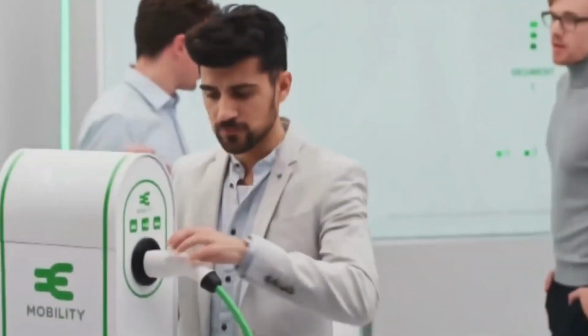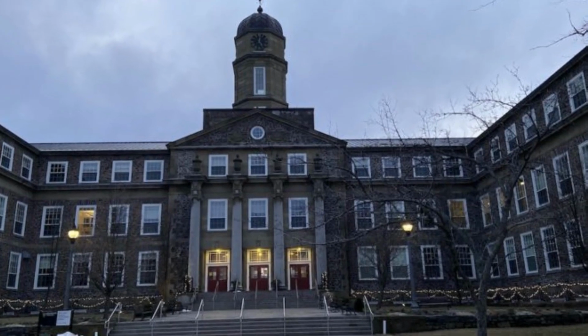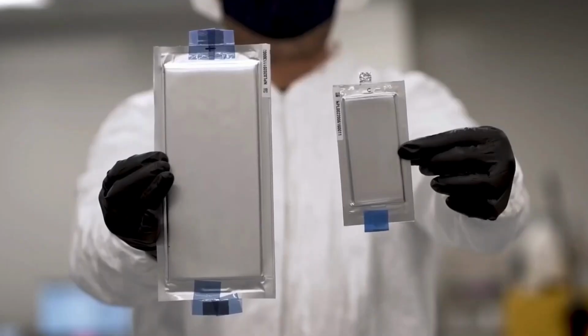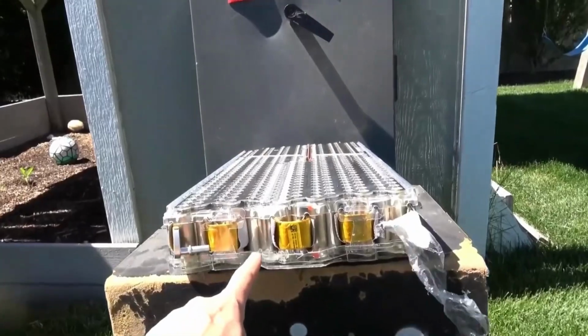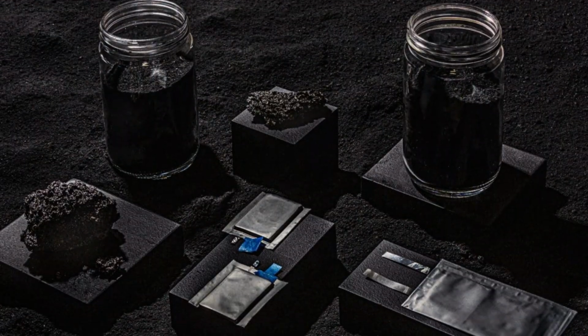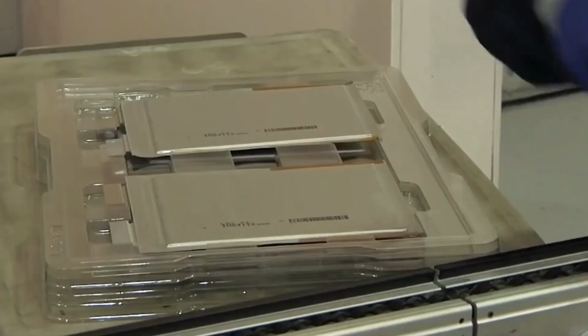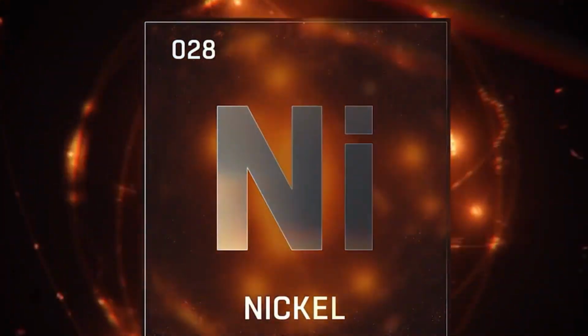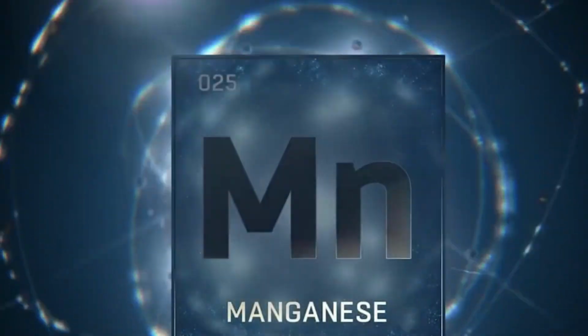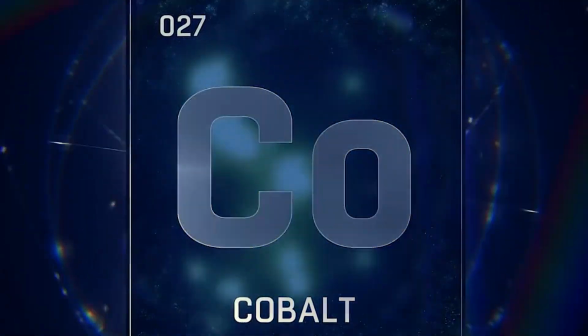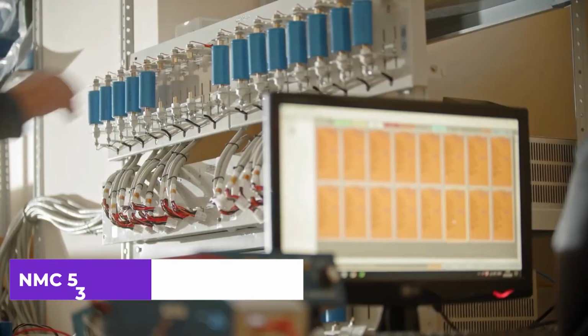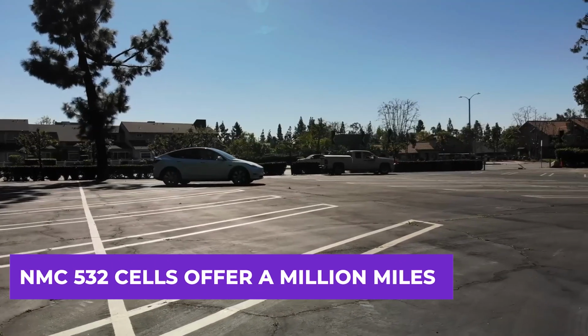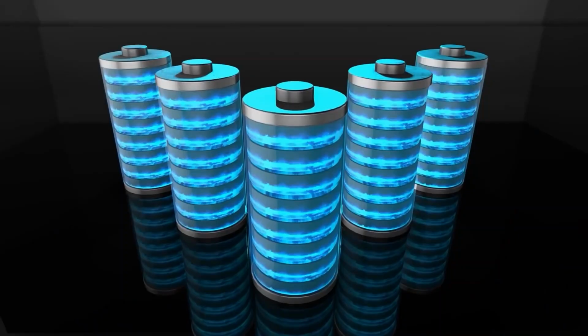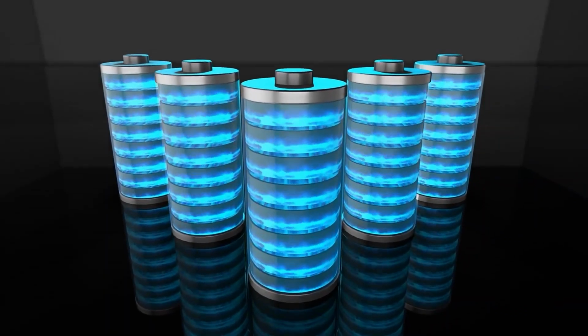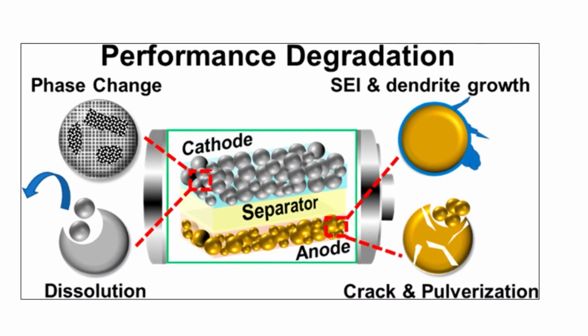Meanwhile, Tesla's research partner, Dalhousie University, has shifted its focus to mid-range batteries using NMC 532 cells made with graphite without silicon. According to research, NMC 532 cells, composed of nickel at 50%, manganese at 30%, and cobalt at 20%, can maintain over 90% of their original capacity even after 1 million miles of usage, leading the media to dub it the million-mile battery. This format minimizes typical degradation issues, such as particle cracking and surface reactivity.